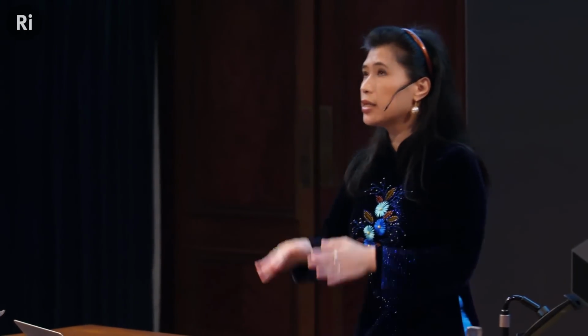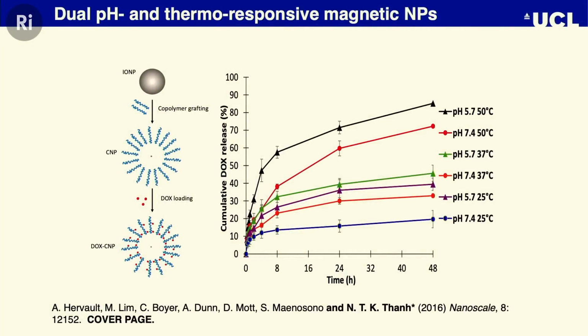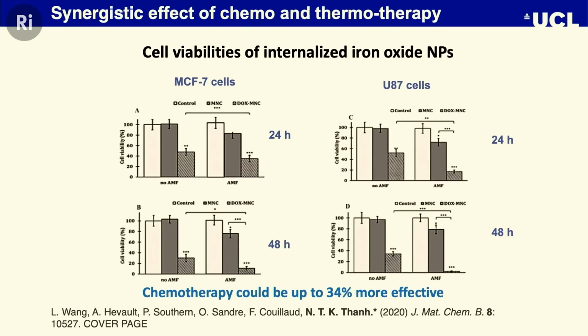And you can see the bottom line, where the pH is 7.4 and the temperature is 25 degrees, low temperature and high pH, and the top line, where you have a high temperature and lower pH, you have a higher drug release there. So we look into this synergistic effect of chemotherapy and magnetic hyperthermia. The data shows two different types of cells, and we incubate them at different times, monitoring after 24 hours and 48 hours.